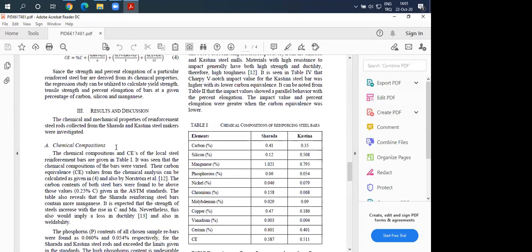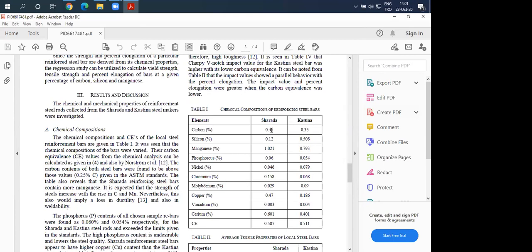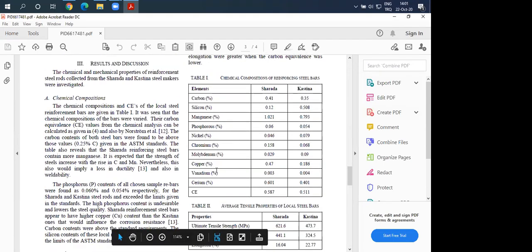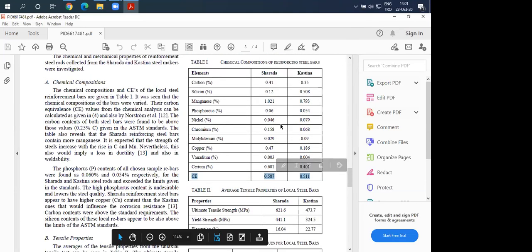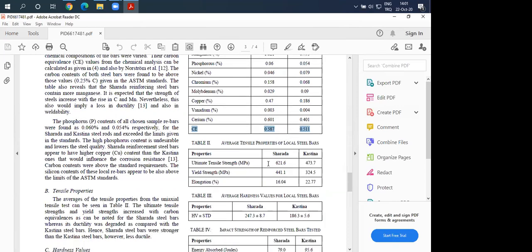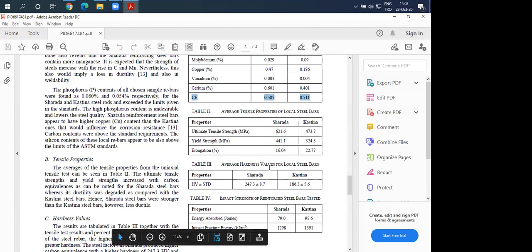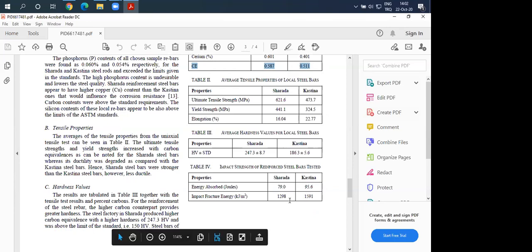So accordingly, the carbon equivalent was determined to be 0.41 for Sharada and 0.35 for Katsina, which are above the levels required. Silicon, manganese, phosphorus, nickel and other chemical compositions were also determined, and their CE value was calculated in comparison. In the tensile test, we found that Sharada Mill Company has a higher ultimate tensile strength of 621 compared to Katsina. Yield strength is also higher for Sharada, but elongation for Sharada is lower, showing that Sharada is producing more brittle material compared to Katsina. The hardness values are also calculated in Vickers, and Charpy test results are also visible in those tables.